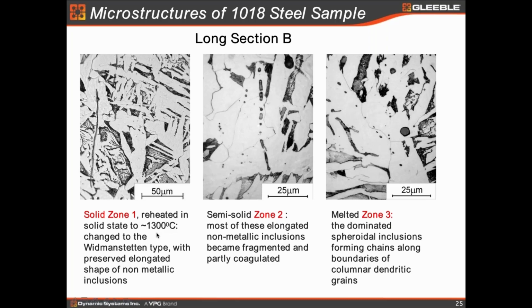We see it's a normal Widmanstätten type of structure, but we have preserved non-metallic inclusions, because this is to show you why it's changing at a different temperature, like the one you see in zone 2, right? And you see some of the non-metallic inclusions have become fragmented, right? Because of the mushy zone, semi-solid zone. And in the fully melted zone, we call it zone 3, we see dominant spherical inclusions along the boundary of the columnar dendrite. So in other words, we can generate a columnar microstructure or an as-cast microstructure.